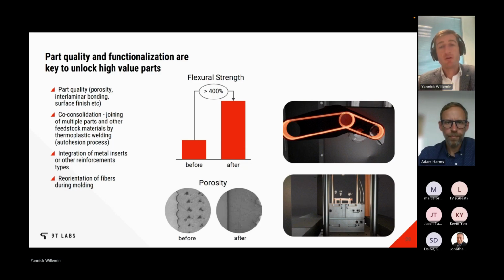Really a part with less than 1% porosity, very flat surface, and these kinds of parts can really go into high performance applications for a longer time. So we speak also fatigue cycles and so on. So the flexural strength, if you take some sampling, you see that there's a huge increase. So it's just a different class of performance.